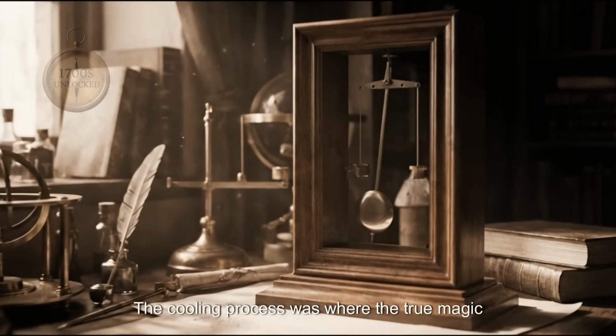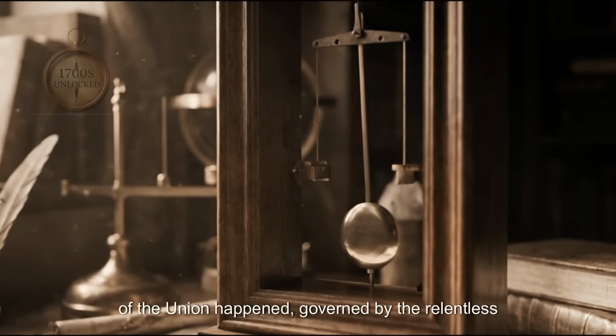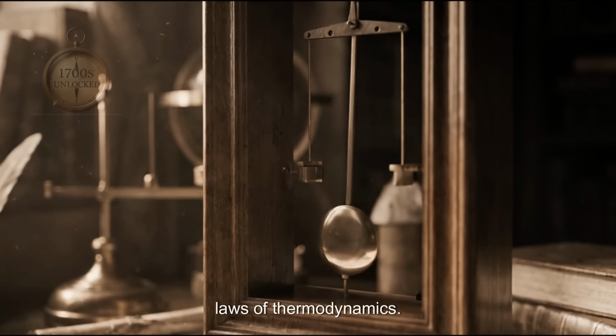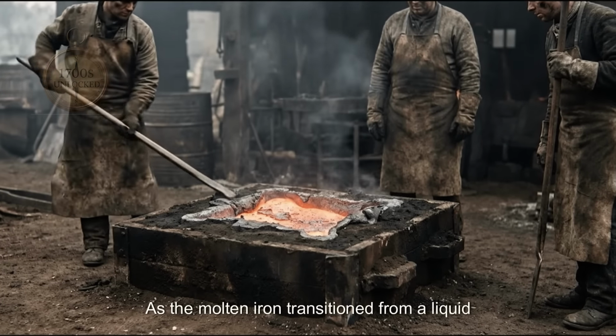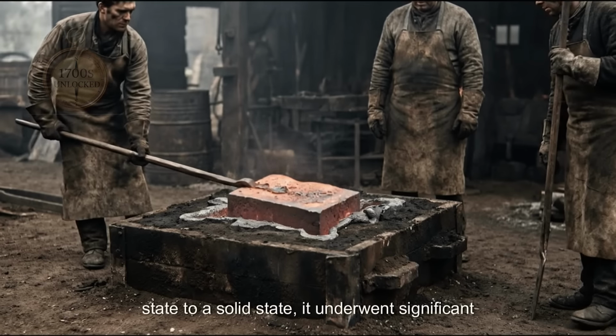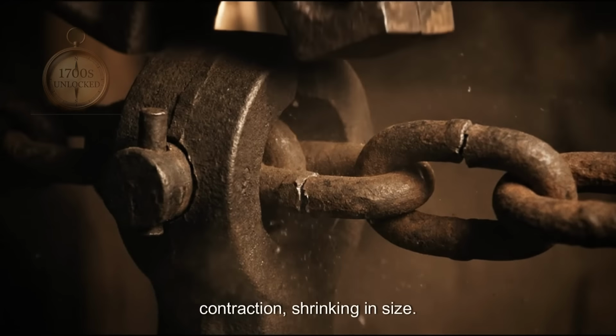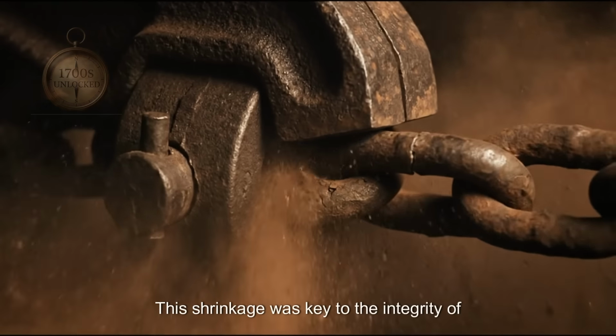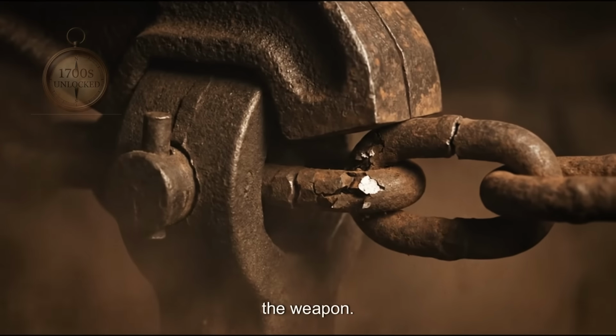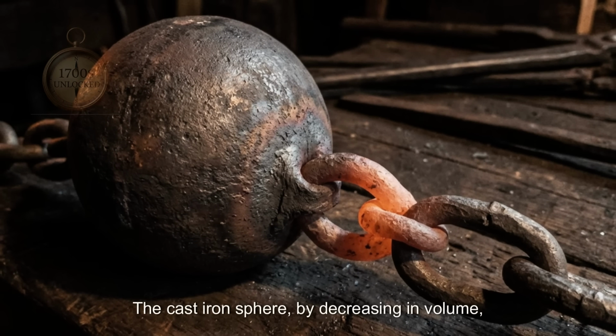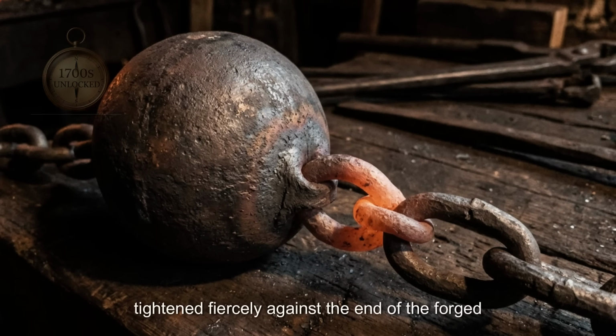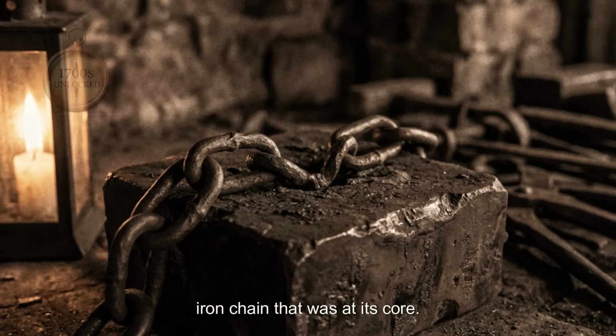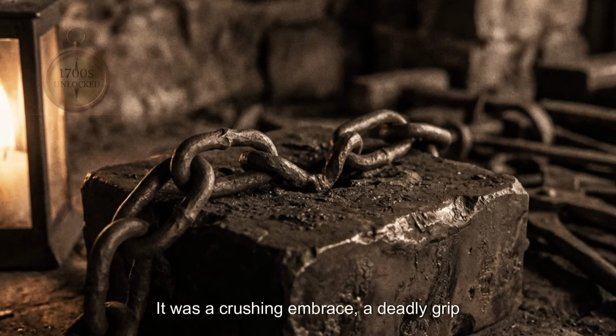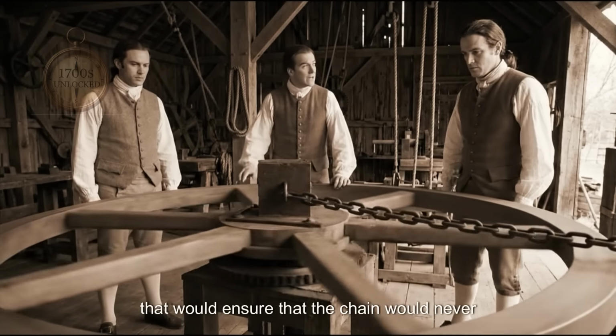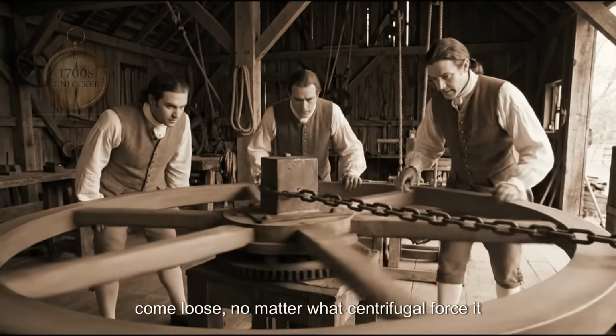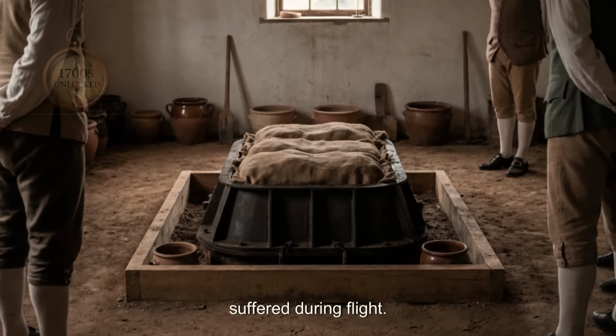The cooling process was where the true magic of the union happened, governed by the relentless laws of thermodynamics. As the molten iron transitioned from a liquid state to a solid state, it underwent significant contraction, shrinking in size. This shrinkage was key to the integrity of the weapon. The cast iron sphere, by decreasing in volume, tightened fiercely against the end of the forged iron chain that was at its core. It was a crushing embrace, a deadly grip that would ensure that the chain would never come loose, no matter what centrifugal force it suffered during flight.